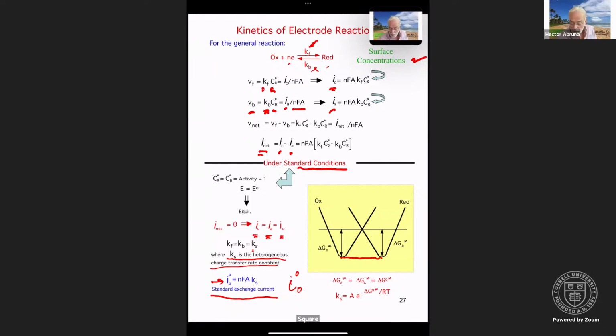Notice there's no driving force. The activation energies for the forward and reverse processes are the same. And so the activation energy for the anodic and the cathodic are one and the same, equals the standard free energy of activation. And so then we can expand and write that ks equals a pre-exponential times e to the minus delta G0 over RT.